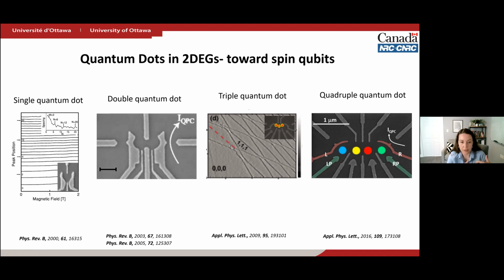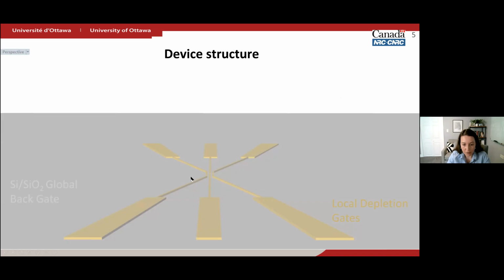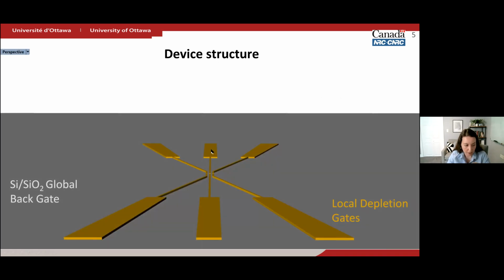We have a direct gap in the monolayer limit, which means that in principle, if you want to create some kind of a light-matter platform, that could be a very efficient way to do it, as well as there's less possibility for interference with the spin state, so longer coherence times might be expected for 2D materials. And so we embarked on this ambitious project to try and use 2D materials and pattern them with gates and see if we can realize quantum dots in this system. It's a very challenging project from a technical point of view. I'll get to that in a second.